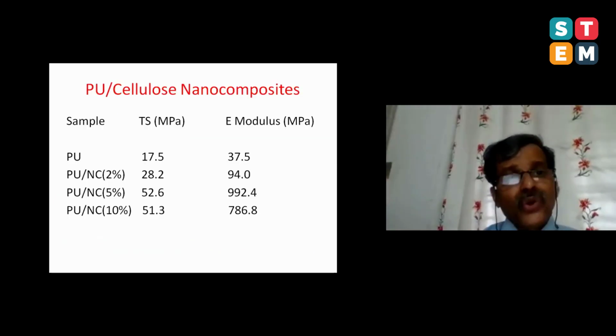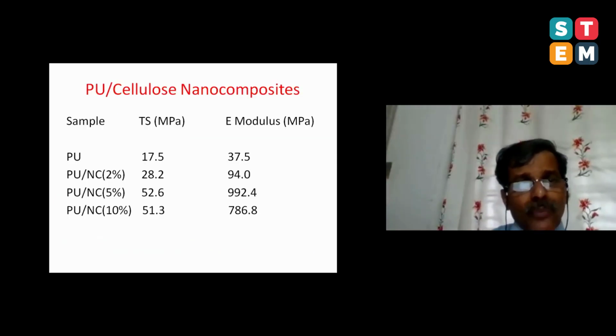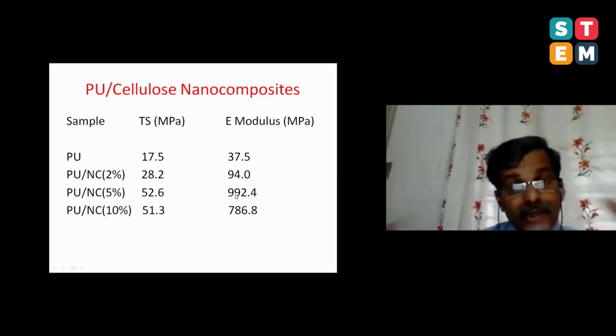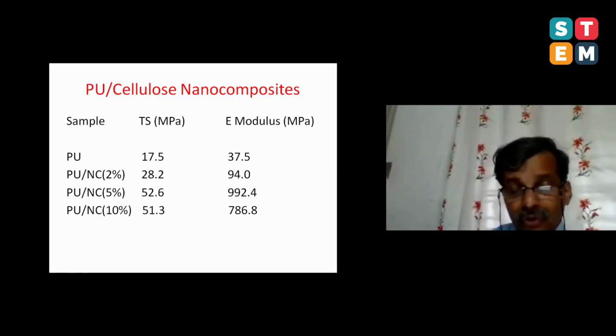I also wanted to show you something very interesting. We had a cooperation with Brazil where we made a polyurethane cellulose nanocomposite. My Brazilian counterpart made a biocompatible polyurethane. The strength of this material is 17.5 megapascal, the modulus is 37.5. If you put in 5% of nanocellulose, the strength becomes 52.6. And the modulus, you can see a quantum jump, 992.4.